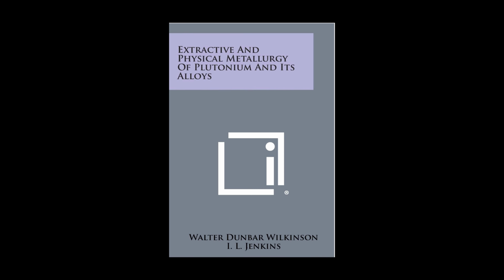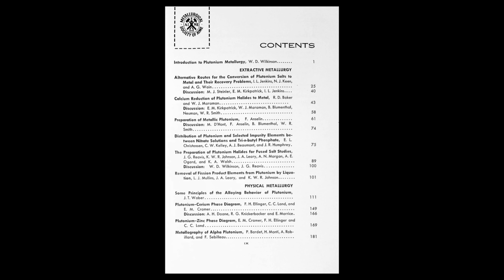But it gets even more intricate, doesn't it? Something about its fundamental structure. Oh, yeah. Plutonium is infamous for its allotropy. Allotropy. That means it changes form, right? Changes form dramatically. Between room temperature and its melting point, about 639 Celsius, it morphs through no fewer than 6 distinct crystal structures. 6. Wow. Yeah, 6. Each one with its own density, its own properties. This constant shifting with relatively small temperature changes has huge implications for mechanical properties.